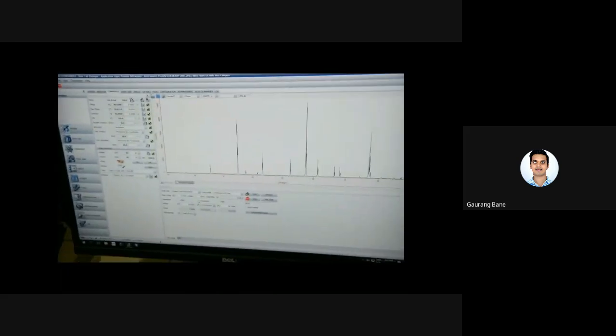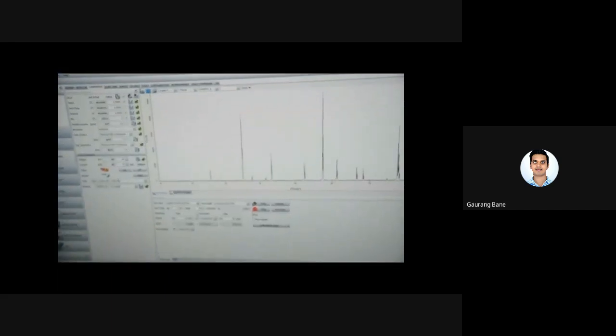Here we are seeing the data of a standard sample. In our case, it is corundum, which is Al2O3. If you see the data, it is giving very nice sharp peaks. It means that the sample is highly crystalline. If you get broad peaks, it shows the sample is amorphous.